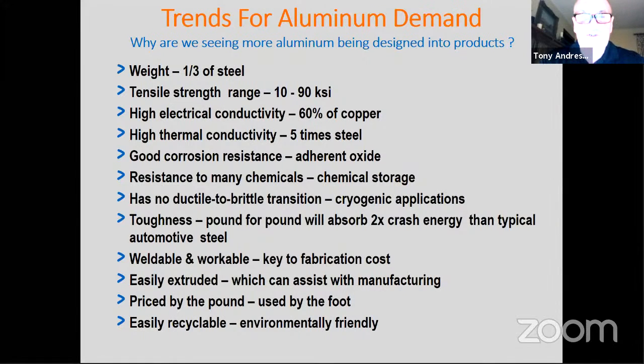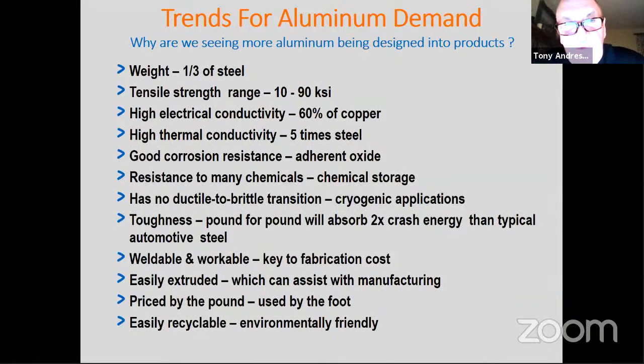But the main consideration there is when we weld it. When we try to weld aluminum, the heat is being pulled away 5 times faster than when we weld steel. So is that a consideration when we design our procedures and we choose our welding equipment? Absolutely. Yes, it is. They talk about welding aluminum hot and fast, and that's what it's all about. You need high current densities, and you need fast travel speeds to prevent lack of fusion.